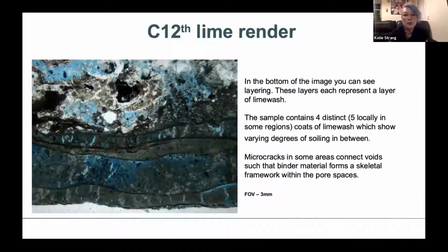But what we were most interested in with this sample was that we could see from the binder itself that it was just quite a normal non-hydraulic lime. So we wanted to find out what was going on with these paint layers. So we did XRD as well on the paint layers that we could isolate, and it did come back as calcium carbonate. So you're basically just looking at lime wash.